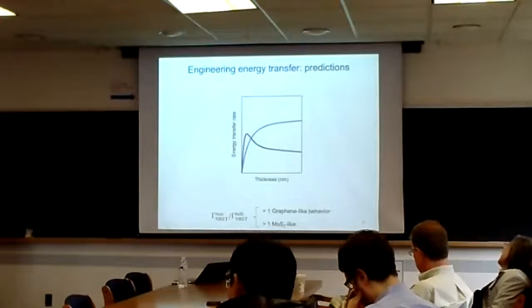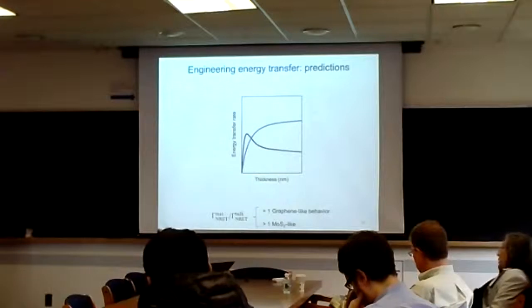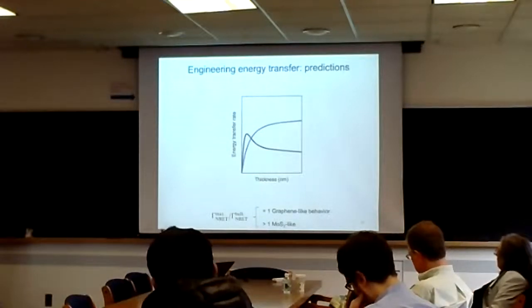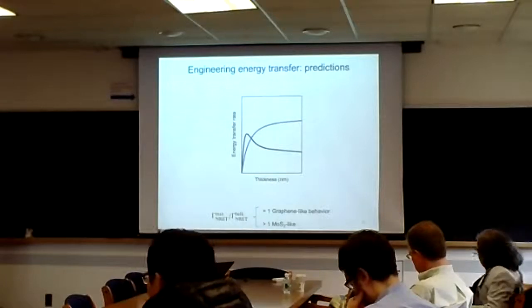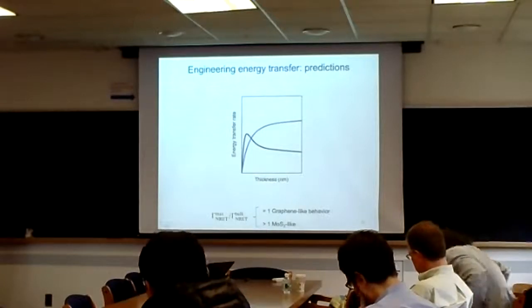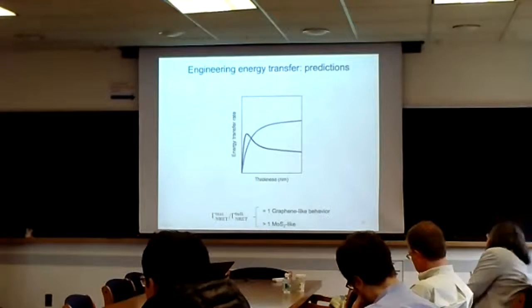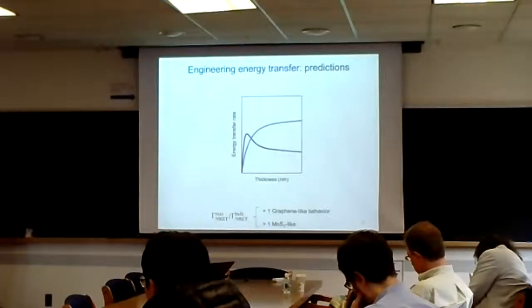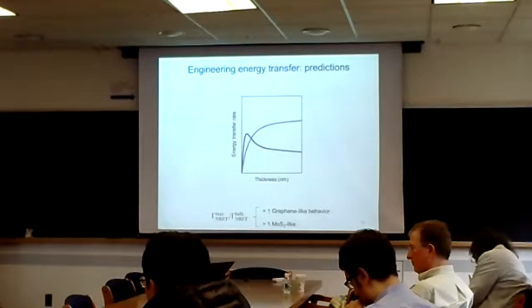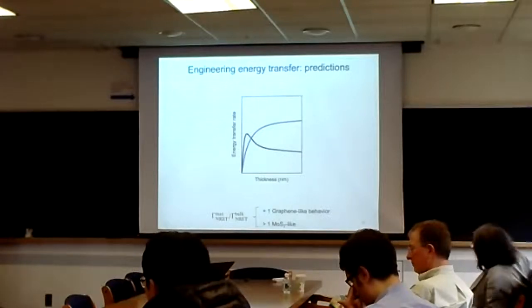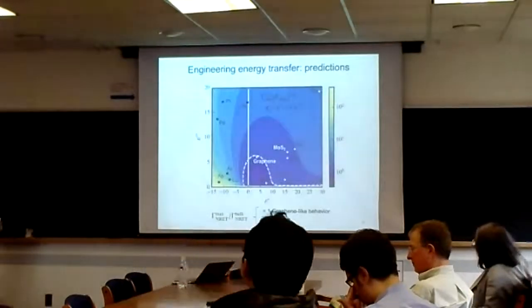So the regime that we're operating in, the excitation densities, we have the results as a function of the excitation density, and that's in a very linear regime where we don't have these other processes going on. So it's basically the Auger process is not nonlinear. Right. So okay.